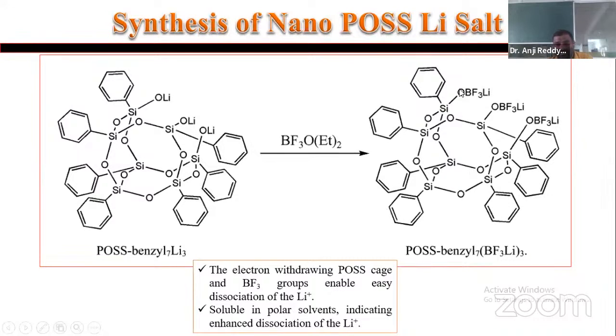Without adding any plasticizer, by using this POSS lithium salt with the PEO, we achieve conductivity of the order of 10 to the minus 4 with good mechanical stability. The electron-withdrawing POSS and the BF3 groups enable easy dissociation of Li+. That's why we replace Li with BF3Li. It is soluble in polar solvents, indicating enhanced dissociation of the lithium ion.